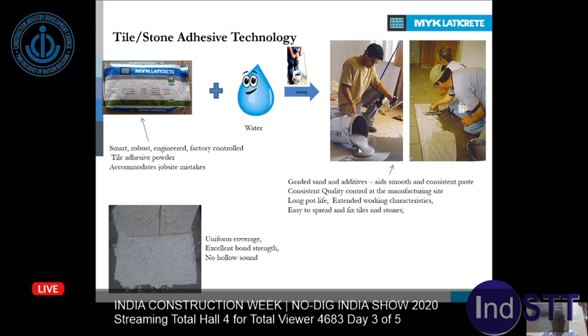It's a good consistency, flowable material, uniform. There are no lumps, there is no water puddle, or there is no thickness. Then you can spread it very thin with a controlled groove thickness. So you don't need more material. You take a very small amount, 3 to 4 mm material, and spread it. Then you fix a tile. The moment you fix a tile, you can see that it's completely uniform and it's sticking to both tiles as well as the substrate.